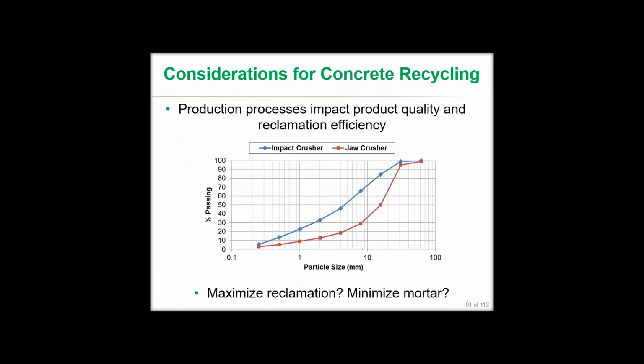Another interesting consideration is the fact that the production of crushed concrete will impact the quality of that material and the reclamation efficiency. And this is a simplified graph. This actually came from a German study. There was a similar one done here in the US back in the 80s as well that showed that when you use an impact crusher, for example, the horizontal or vertical impact crushers, they do a wonderful job of removing the mortar from the exterior of the aggregate particles.